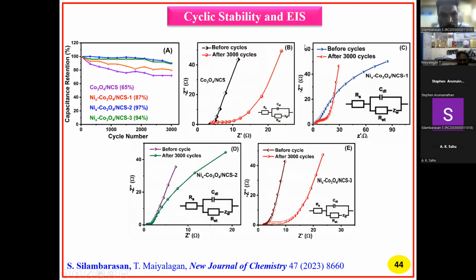Next, the cyclic stability. Here we took the cycling up to 3000 cycles. For retention percentage, sample 2 has 97%, and compared to the other samples it gives more retention percentage.